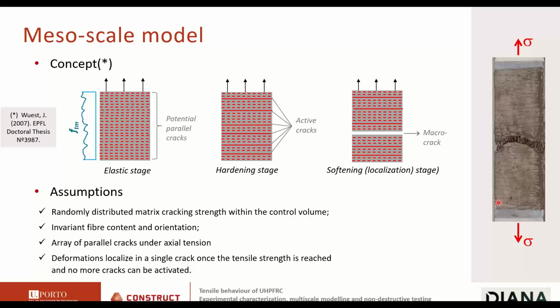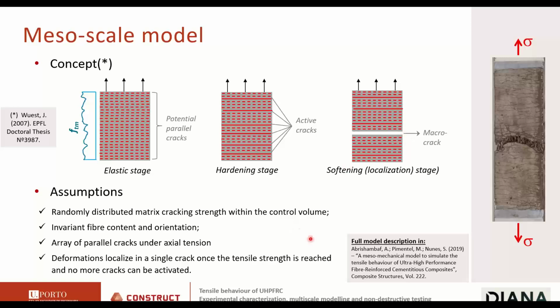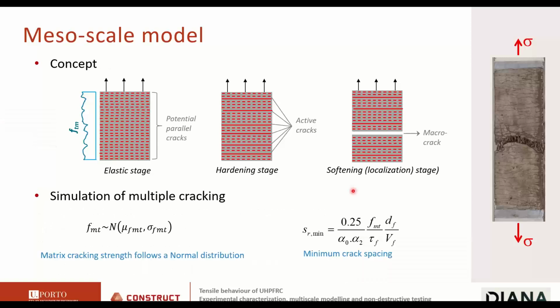We consider that these cracks can be idealized or modeled as an array of parallel cracks. Well, in reality, it's a little bit more complicated. Sometimes you see some branching, some tortuous shapes, but we are modeling this as parallel cracks. And the deformation is localized in this crack once the tensile strength is reached, and at this point no more cracks can be activated because they're actually unloading. So the full model description can be found on this page.